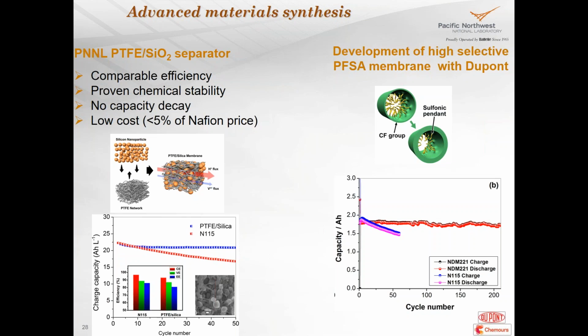And also we have a collaboration with DuPont, which is called Chemours now, formerly DuPont, to address the capacity decay issue of the Nafion in the vanadium flow battery. What we do is we make the pores of the Nafion much smaller to prevent the crossover of the vanadium ions. And from this lower right figure, you can see the new membrane in the red line is much more stable than the pink and the blue lines of the Nafion 115.